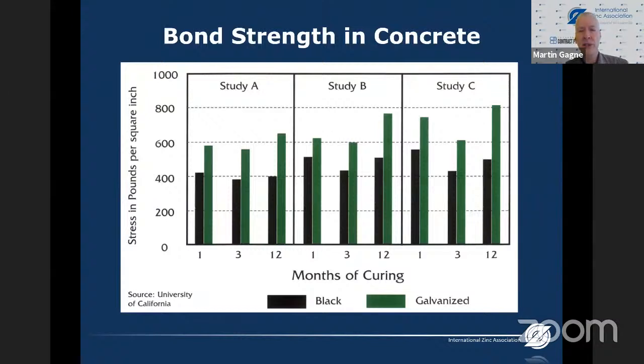Now, the bond strength of zinc with the concrete is very good. This is a graph from the University of California. They look at the bond strength between black steel and galvanized steel. The black bars are for black steel and the green bars are for galvanized steel, depending on the month of curing. So this study was repeated 3 times with different types of concrete, but we can see that the galvanized steel has superior bond strength over all conditions and all curing times.